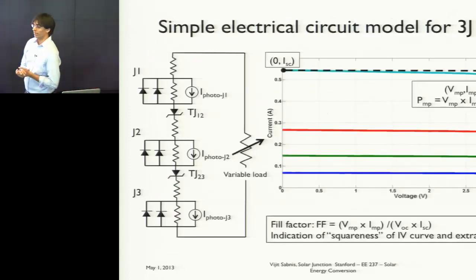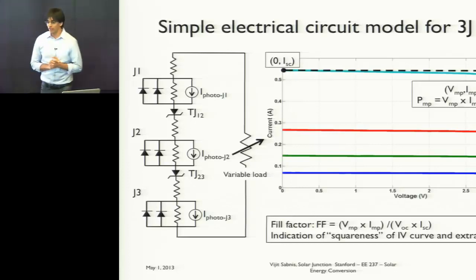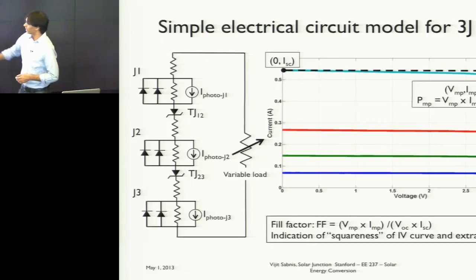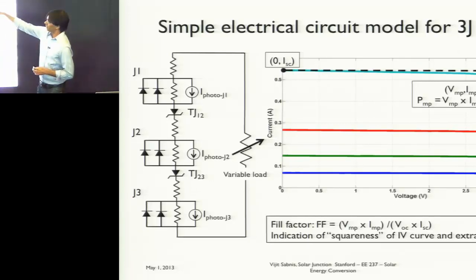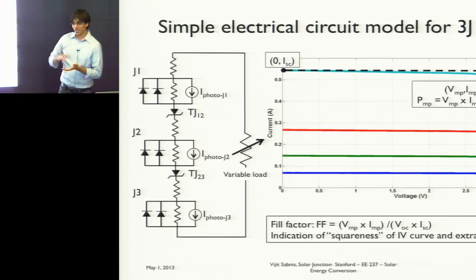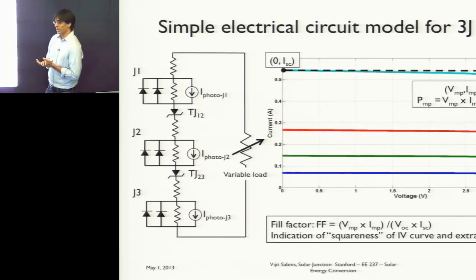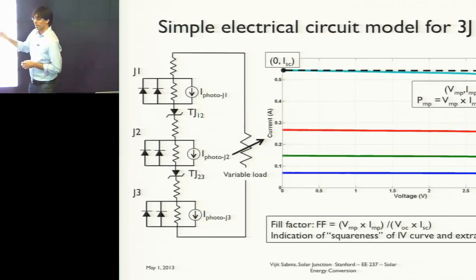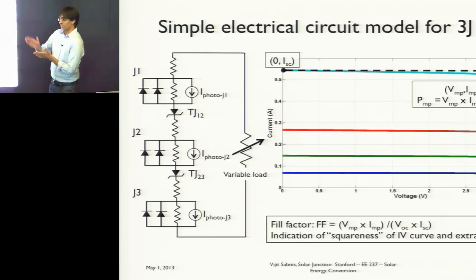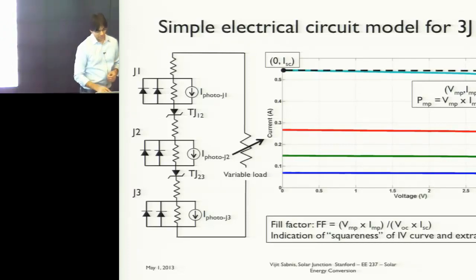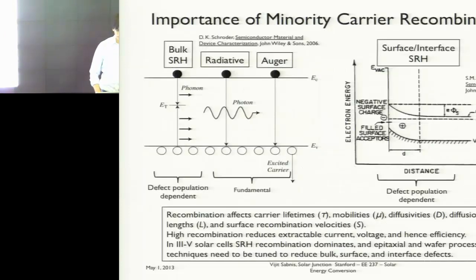And as you can imagine, this is a very simple circuit model of these solar cells. And what you'll see under concentration, as this is actually real data that we took in my lab, as you increase in concentration, your current will go up linearly with concentration. So if you go from 1 sun to 1,000 suns, you will get 1,000 times more current. That doesn't do anything for you in terms of efficiency. But the real key here that's interesting is your voltage actually goes up with concentration. So as you put more light onto your solar cell, your quasi-Fermi levels actually get driven towards the band gap, and that means the voltage produced out of each junction increases, and this is why the efficiency increases under concentration. And that's something that's very different compared to a regular PV cell operating at 1 sun.